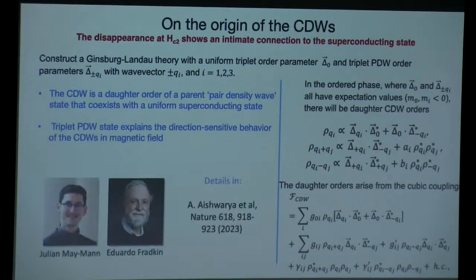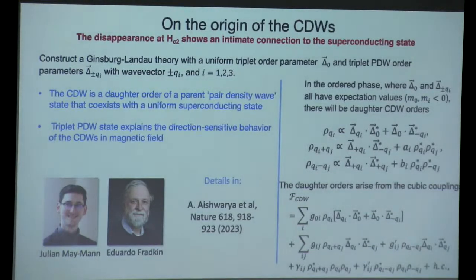This triplet pair density wave state explains the magnetic field sensitivity, because when you turn on a magnetic field, you get vortices, and these vortices suppress both the uniform component as well as the pair density wave. When both of them disappear, the charge density wave also disappears.